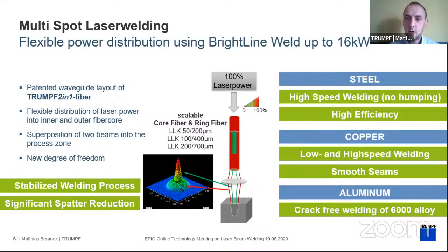It is suitable for all materials we see in e-mobility and, of course, other industries. In steel, we will get a high speed gain, which means exceeding 20 meters per minute, 30 meters per minute welding speeds. This is extreme and crazy what's going on here, as well as having a higher efficiency, meaning power can be reduced to achieve the same welding depth.